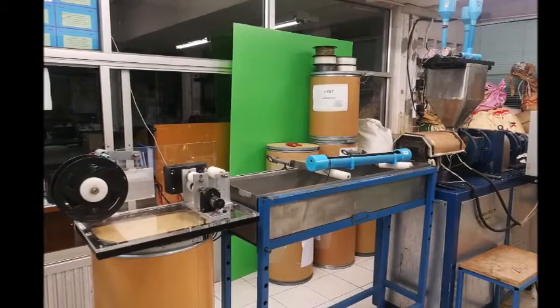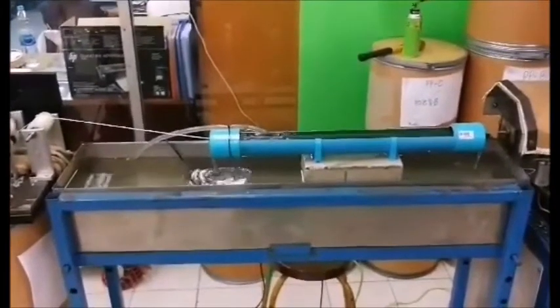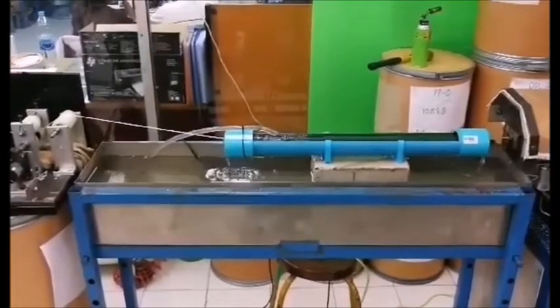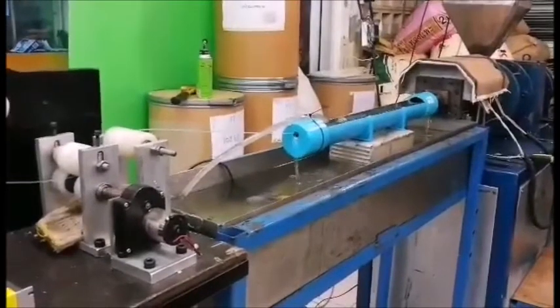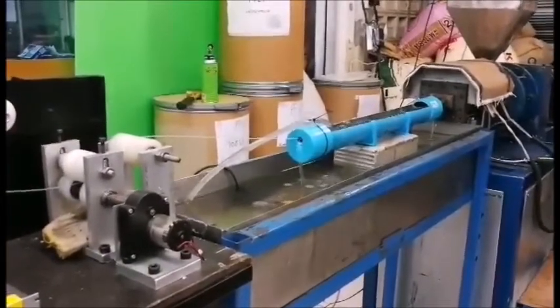There are 3 steps in the pulling plastic process. First, the plastic beads are filled into the hopper at 20 grams per minute, using a melting temperature of 175 degrees Celsius. Then the plastic beads are pulled into plastic filament by pulling through the cooling unit to set the plastic filament. After that, pull the plastic filament into the plastic spool unit, then adjust the motor speed to set the diameter of the filament to 1.75 mm.